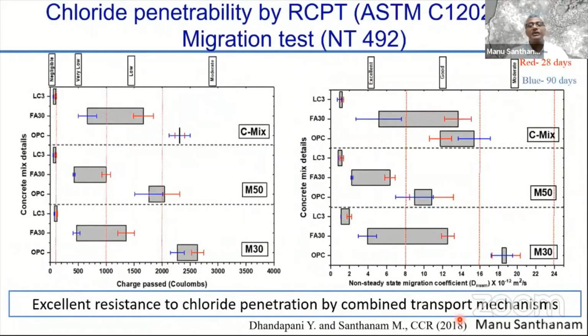The durability is where you can actually see the benefits significantly. On the left, you have the chloride penetrability measured as per the ASTM tests. I know that a lot of people like that test and a lot of people don't like the test, but nevertheless, it is here for people to look at. You can see the ordinary Portland cement related concretes are all in the moderate permeability range. Your fly ash concretes, depending upon the extent of curing, can go into the very low permeability ranges also. But in terms of the LC3, even at 28 days of curing, you are at negligible levels of permeability.